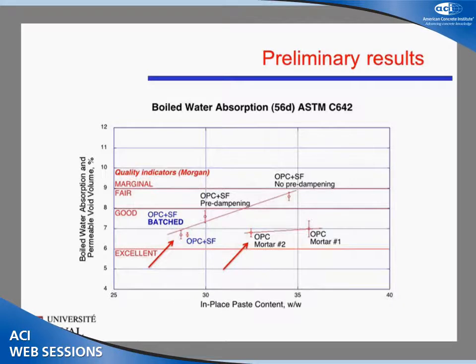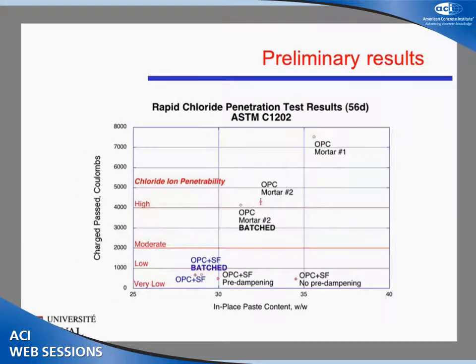And then what about chloride penetration? This is something else. The one thing that is worth mentioning here is that all the mixes in the bottom are silica fume. There's a lot of literature that exists on the effect of silica fume, as well as other cementitious materials, on ion transport, or rather on conductivity of the pore solution. So if you look in literature, you'll find that silica fume plays a big role in that, and that these results may not necessarily represent equivalent OPC material.